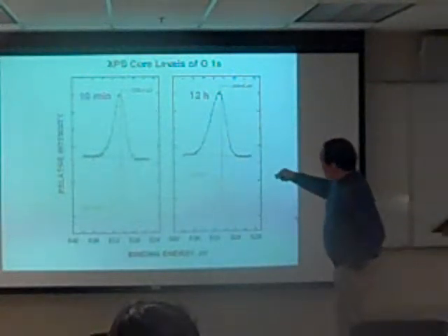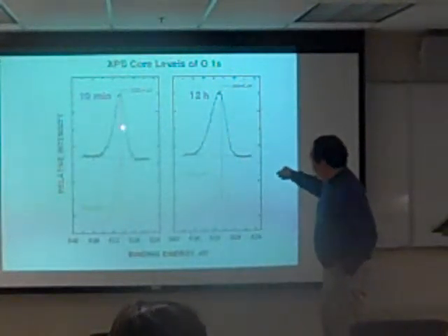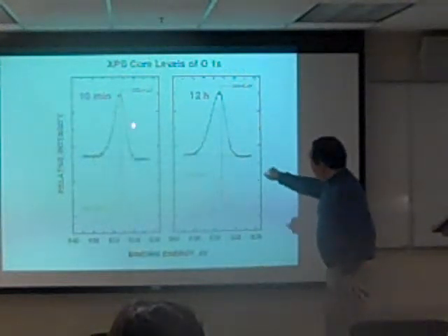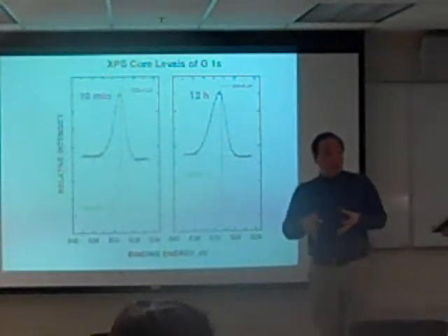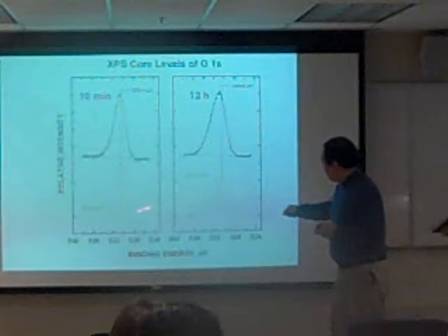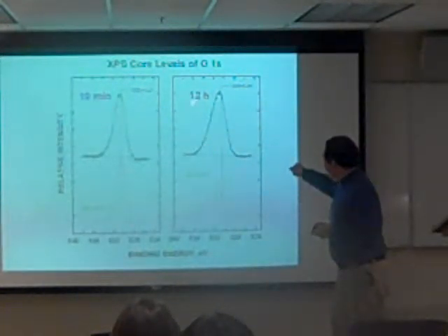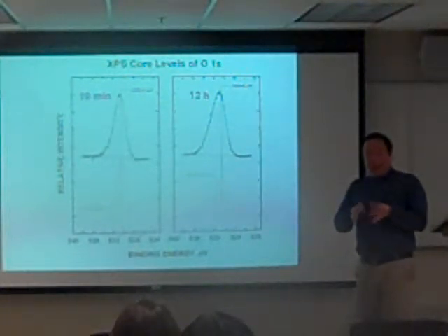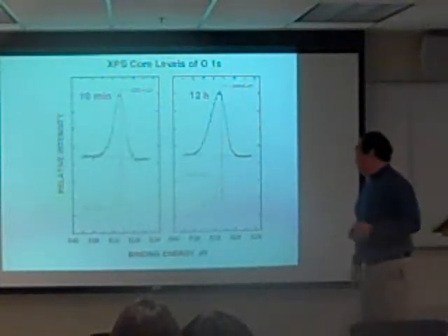And so this is what the XPS data looks like. This is after the TiO2 was exposed to solution for 10 minutes and 12 hours. This is the oxygen from the TiO2. This is oxygen from material that's adsorbed onto the surface. So you can see that there is a growth of this oxidation state. This is after 12 hours. So we can monitor the kinetics of growth by looking at the integrated peak areas of the electron spectrum.